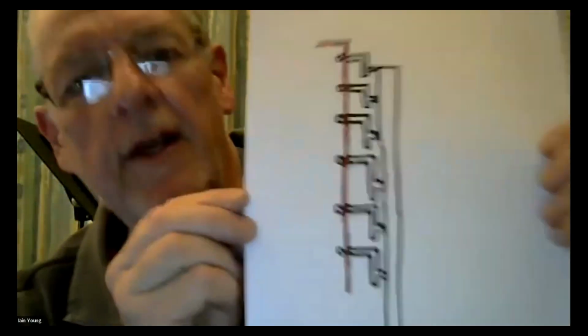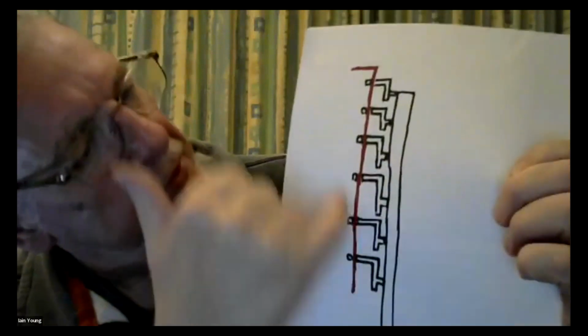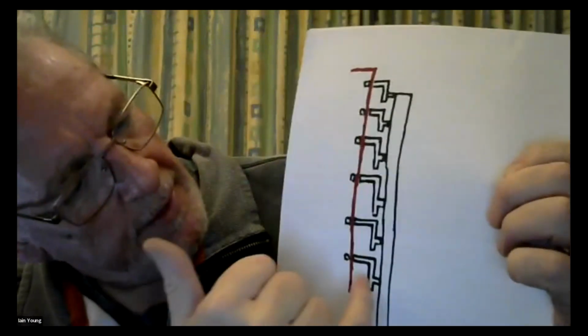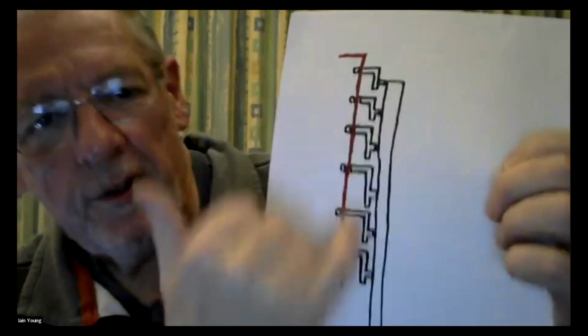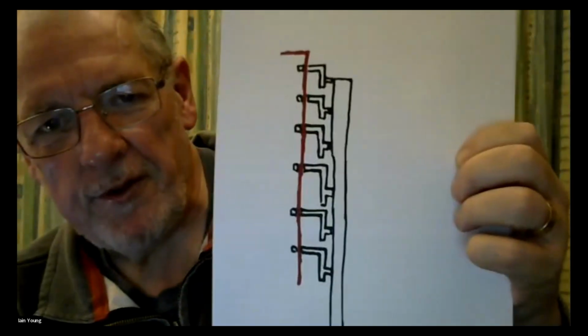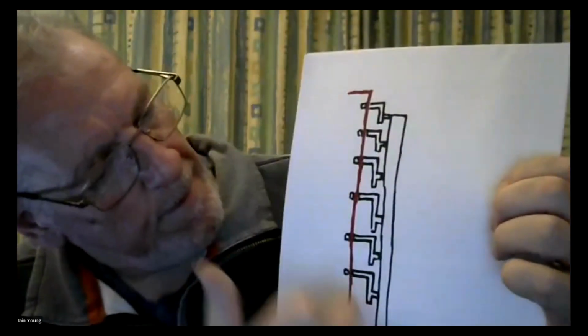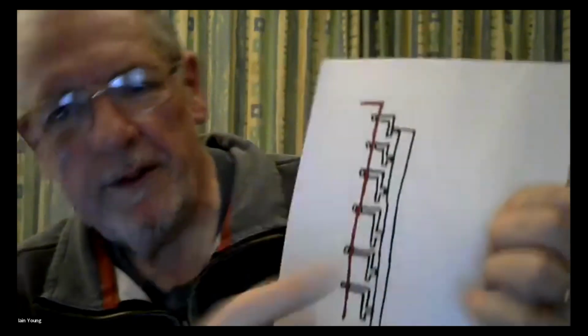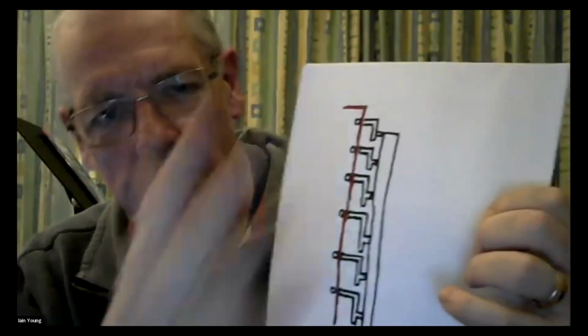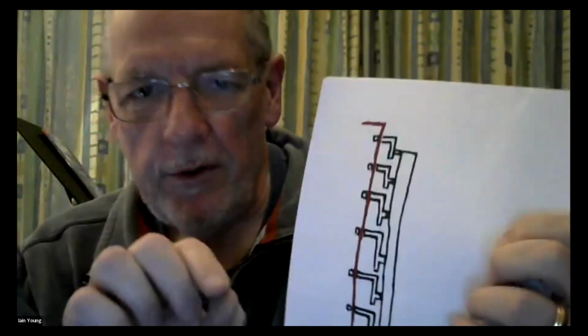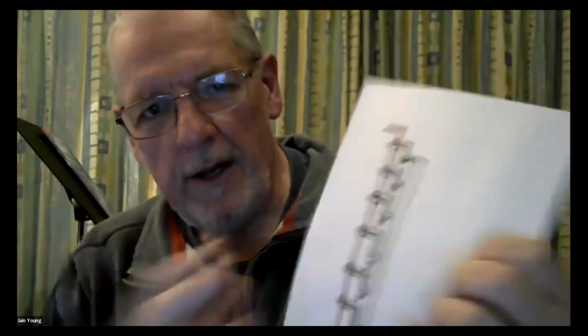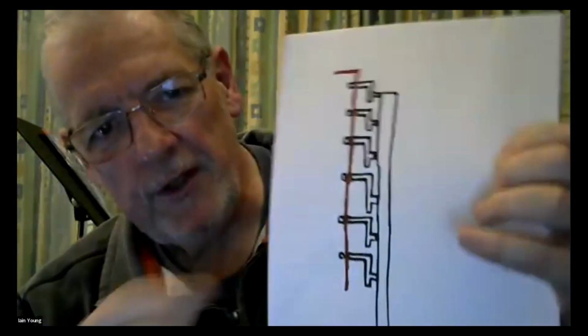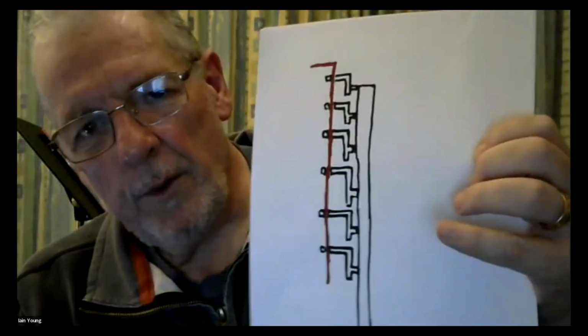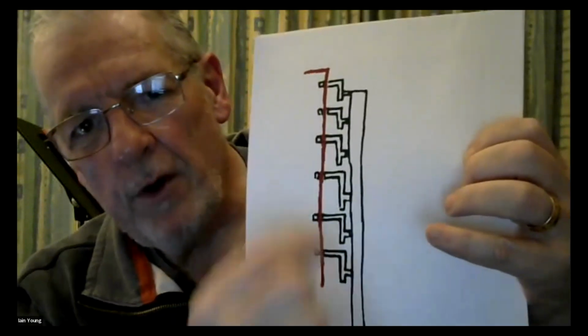Right, and using cores again allows you to put holes into things. Now I've done a little diagram here. So this is a piece of wire in the mold, and these are like your brake hanger brackets off the frames. Yeah, that's your main sprue, right? A piece of wire is in the mold. The wax is injected into the mold around that piece of wire. Before the mold is opened up, you pull the piece of wire out, you open the mold, take the wax out, and you end up with a sprue of waxes which have holes all the way through them.